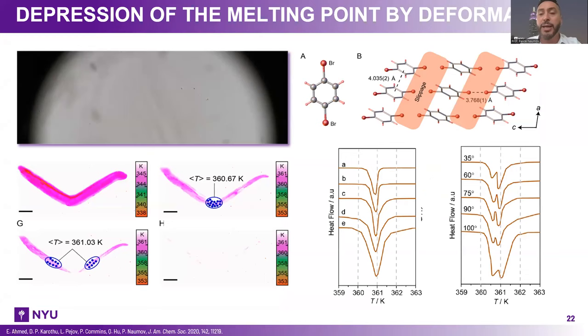And now we know that if you bend a crystal, you introduce so many defects that you can actually alter the melting point. It decreases by 0.3 to 0.4 Kelvin. It's a small decrease, but it shows that the basic physical properties of the material are affected when you deform it, which kind of makes sense, but this is a more quantitative way to look at the same phenomena.